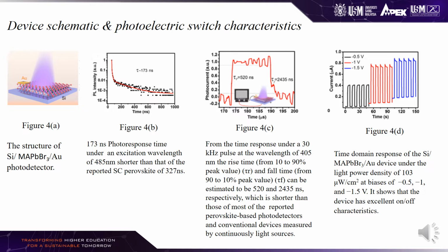This slide shows the device schematic and photoelectric switch characteristics. Figure 4a shows the structure of the silicon MAPbBr3 gold photodetector. 173 nanosecond photoresponse time under an excitation wavelength of 485 nanometers is shorter than that of the reported single crystal perovskite of 327 nanoseconds, shown in figure 4b.